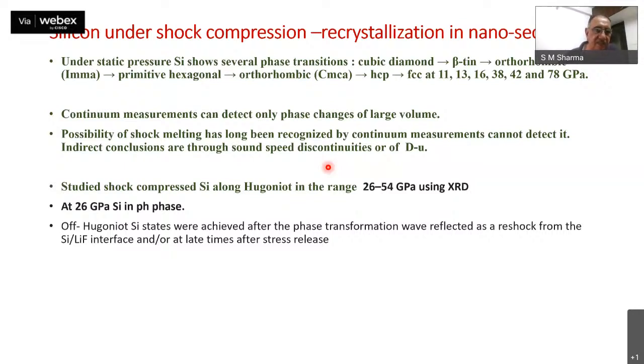So we investigated silicon along the Hugoniot in the stress range from 26 to 54 GPa using XRD. And at 26 GPa, it was confirmed to exist in the primitive hexagonal phase. We also studied what one calls off-Hugoniot states. And what turned out was that once the Hugoniot has gone into a liquid phase, if you shock it for a little more stress, it crystallizes. And the crystalline features are representative of what the phase diagram would suggest at that particular stress.